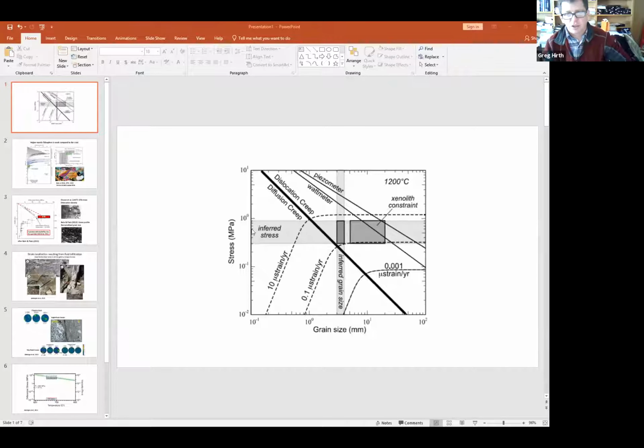So he gets a stress estimate, a grain size estimate of diffusion creep, but also we can predict a grain size from Mark's grain size model. And so Mark's grain size model plots along this line here. And for the inferred stress from Andy's model, xenoliths that come from this area that preserve temperatures of like 1200 degrees have this range of grain sizes. So what is this plot showing?